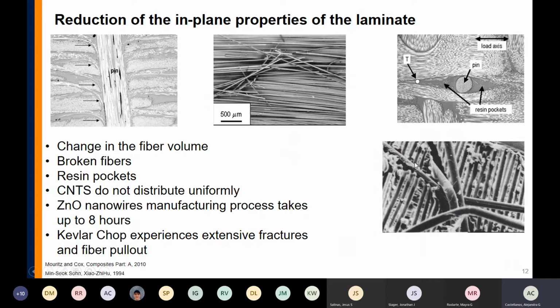And then in the case of the chopped Kevlar, there have been extensive fractures and fiber pullout, as you can see here. And obviously there are carbon nanotubes, but the problem with the carbon nanotubes is that when they start applying the carbon nanotubes on the layers of the composite, they do not distribute uniformly. They tend to agglomerate. So you will have a part that is really, really reinforced, and then the other part of your composite, there will be no reinforcement at all.